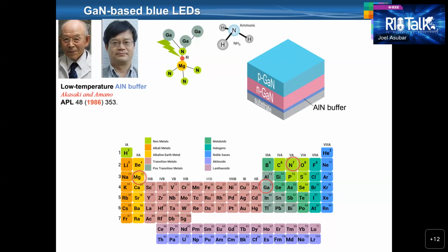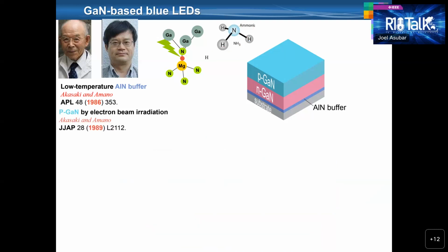But even when gallium nitride is doped with magnesium, holes were not actually generated. This was due to the fact that magnesium was passivated with hydrogen atoms, preventing magnesium atoms from acting as acceptors. I should mention that for the growth of gallium nitride, ammonia gas, NH3, is used as the source of nitrogen. And the associated hydrogen atoms from ammonia form the magnesium-hydrogen complex. Eventually, in 1989, Professors Akasaki and Amano succeeded in realizing a P-type GaN after irradiating a low-energy electron beam on magnesium-doped gallium nitride.